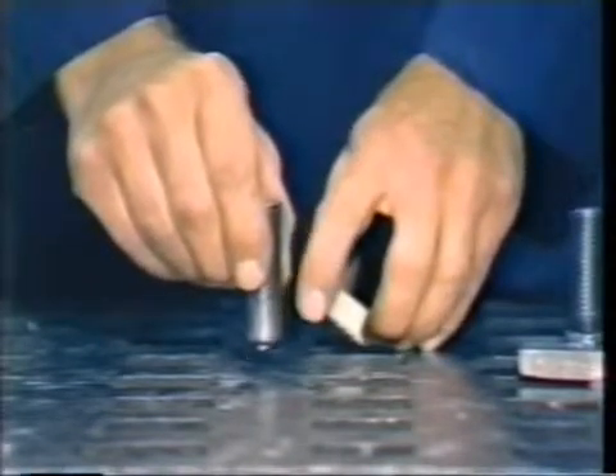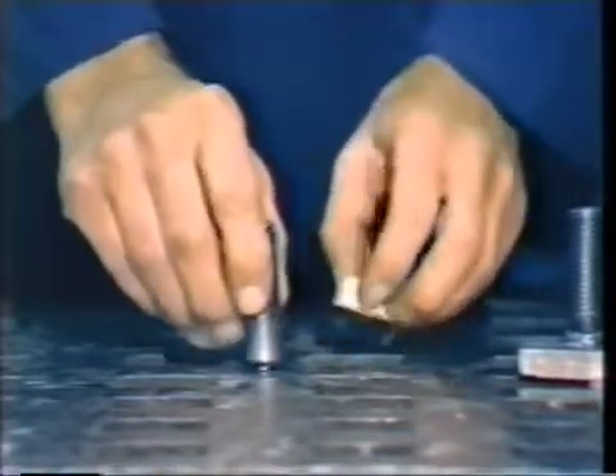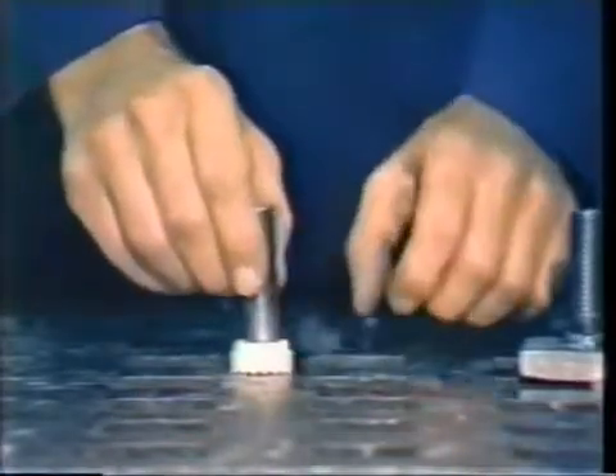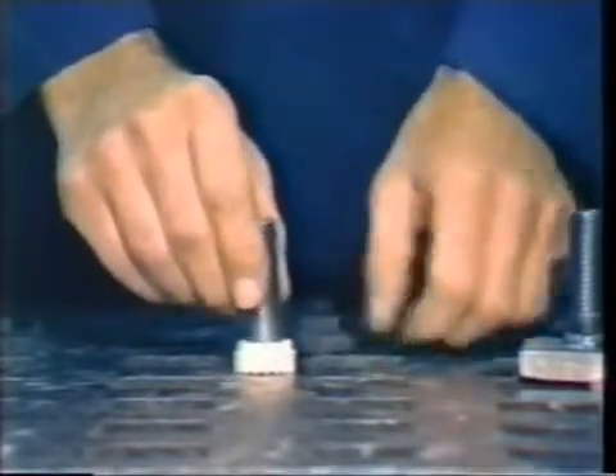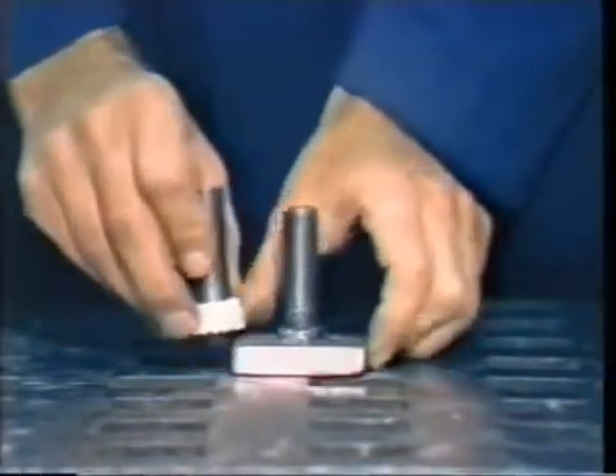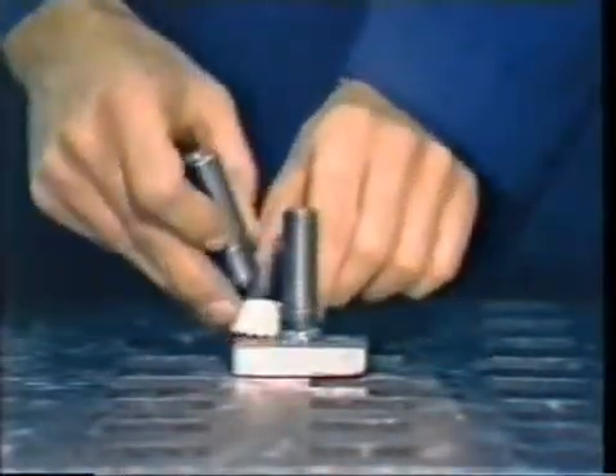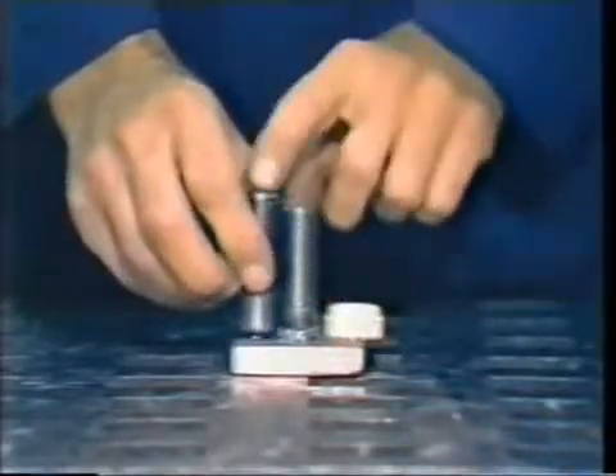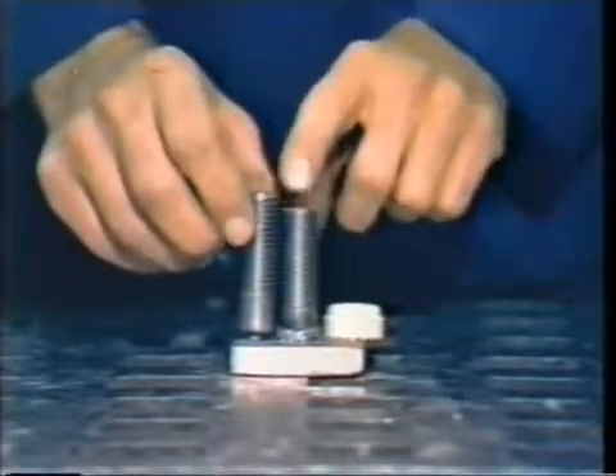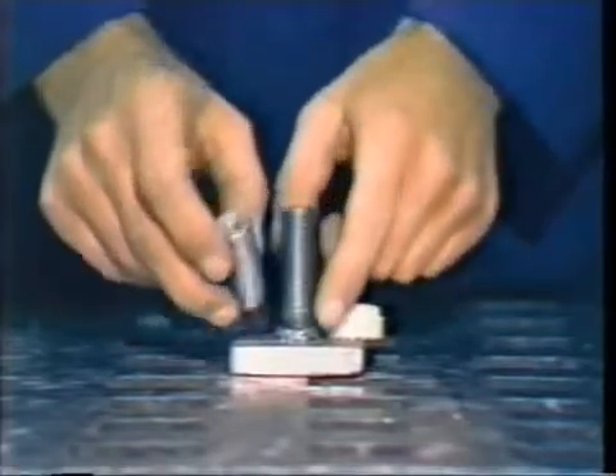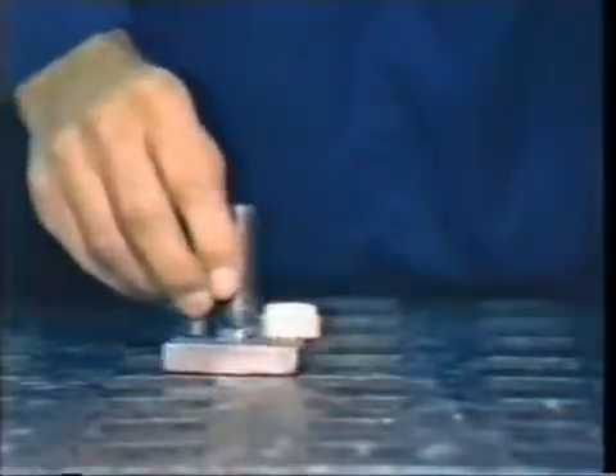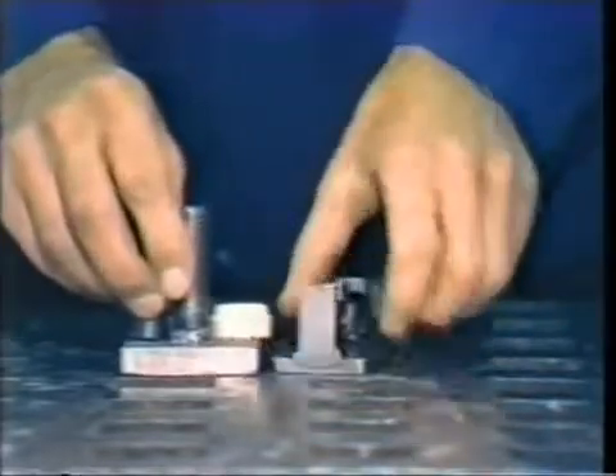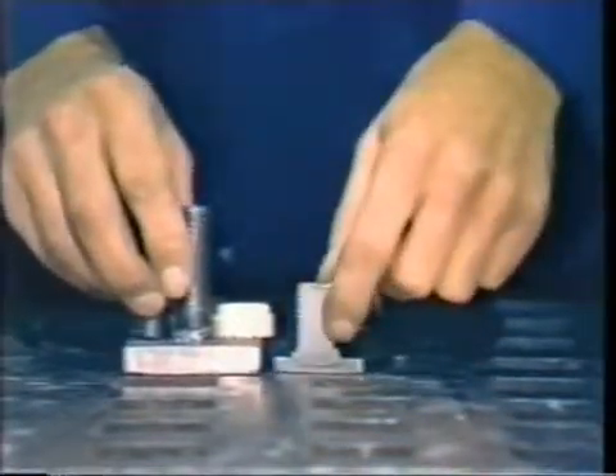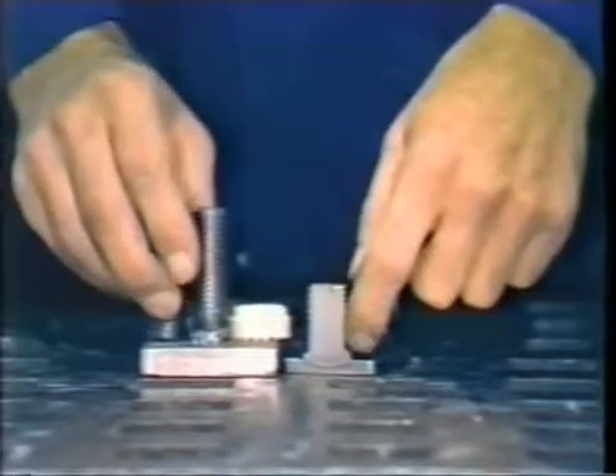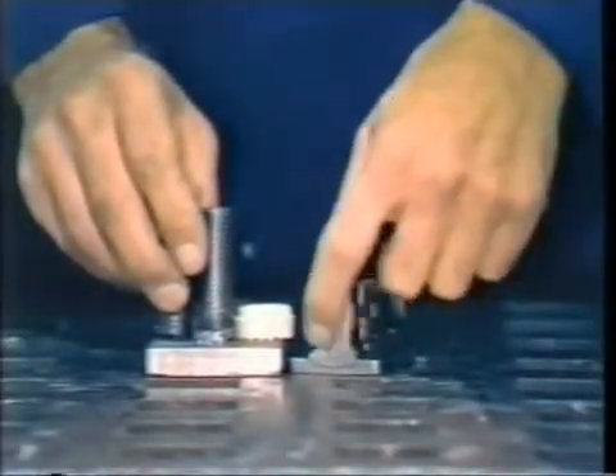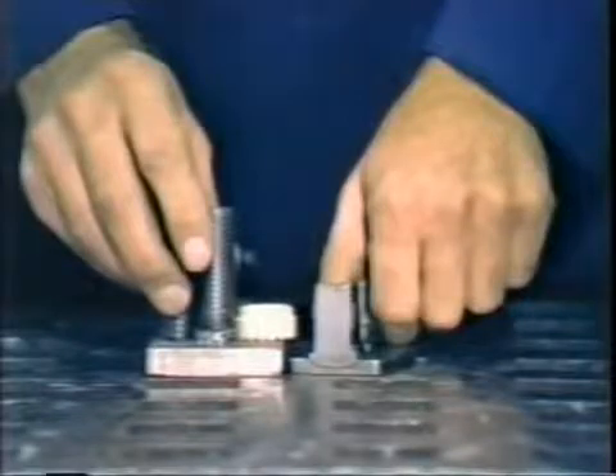At the end of the weld cycle, the stud is released and plunges into the molten pool of metal contained by the ceramic ferrule. In the weld that results, the fillet development is uniform. The length of the stud has been shortened by the burn-off length during the weld process. In the cross-section, we're treating the stud as an electrode. The whole end of the stud is burned off, and you get a cross-section of a sound, dense weld.